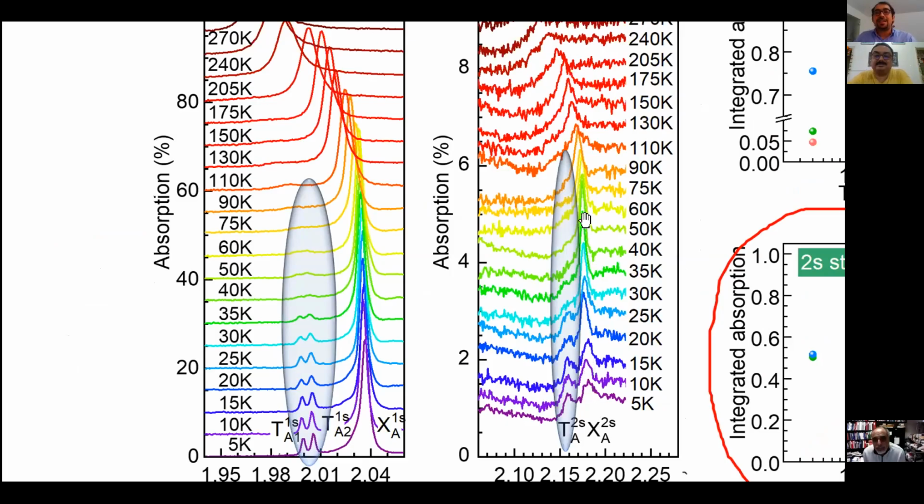And this is a very interesting effect. In fact, it falls exactly in the explanation we were trying to give in this paper: initially there is a state to which the exciton can relax, or the exciton can be converted to a trion. Therefore its line width is large. Now this state disappears and this relaxation channel is gone, and then the line width becomes small because its lifetime becomes large. In this paper we have actually plotted this line width versus temperature, and it's a very interesting effect for sure.